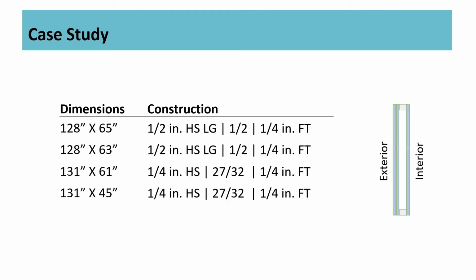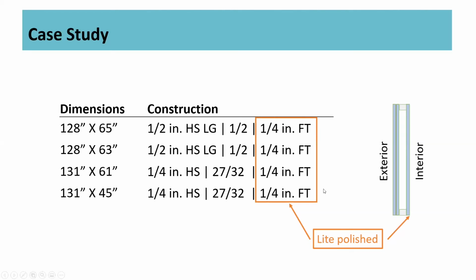So with that, let's put some numbers to it. In this case study, this actually goes back to that chop saw blasting hot metal into the interior fully tempered piece of glass. And so what we're going to be focused on here is this 1/4 inch fully tempered interior piece of glass. And what we were trying to get rid of was something not unlike weld splatter that was coming off of that chop saw. And we have various different lite sizes, as we would anticipate on a new structure these days.